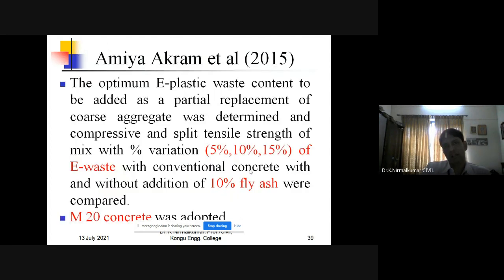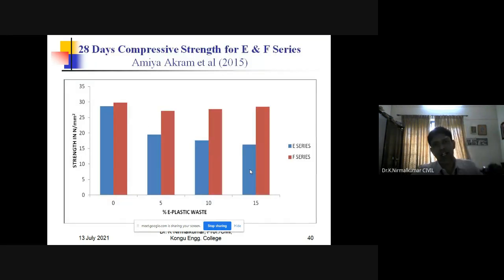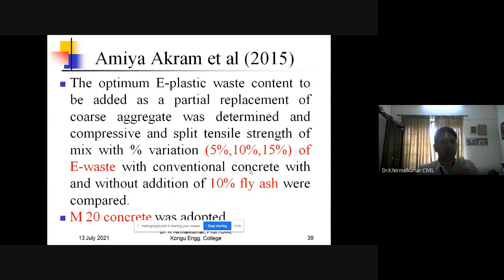Then Amiya Akram et al. in 2015 did the experiment. They determined the compressive strength and split tensile strength, and he varied the mix percentage from 5, 10, and 15%, and compared it with the conventional one. He had used 10% fly ash. Fly ash is a pozzolanic material, and he did it for M20 grade of concrete.